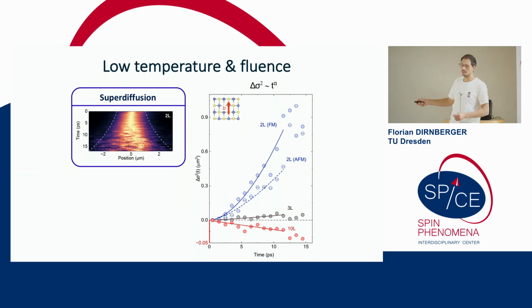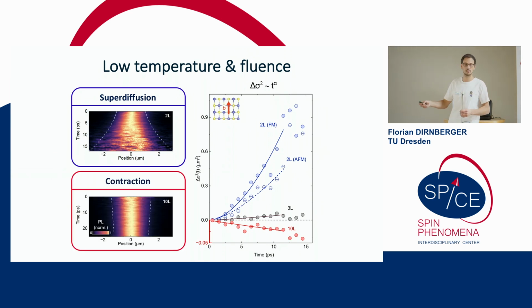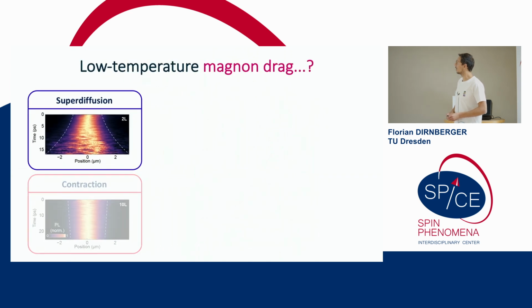We see, instead of this fast expansion, a contraction of the exciton cloud. So we see this sort of negative transport, and the excitons no longer seem to be moving away from the excitation region. They're sort of pulled backwards. This is, again, quite an interesting phenomenon to observe, and it's very rare to see that in this type of experiment.